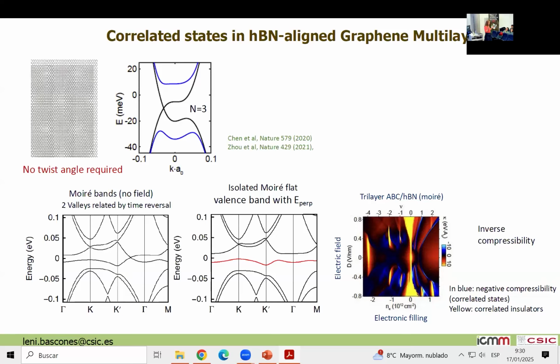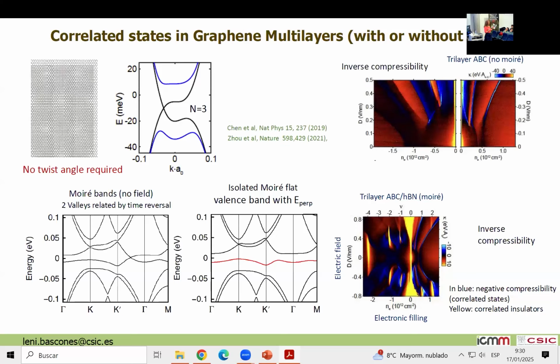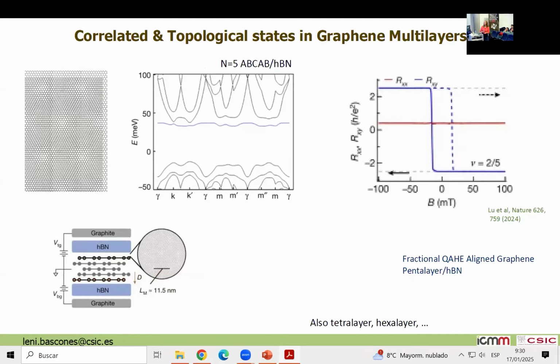Here people have also looked without the moire, without the boron nitride, and some of these states appear. So there is a bit of discussion now about how important the moire pattern really is, but for some states it's for sure clear. In particular, one of these systems, the pentalayer, has been seen recently to be the second system among all the known materials in which the fractional quantum anomalous Hall effect has been seen. The first material was discovered only a few months before in another moire compound. And now there are other systems, the tetralayer and the hexalayer, that are also giving a lot of novel states. So we are not bored in this field.